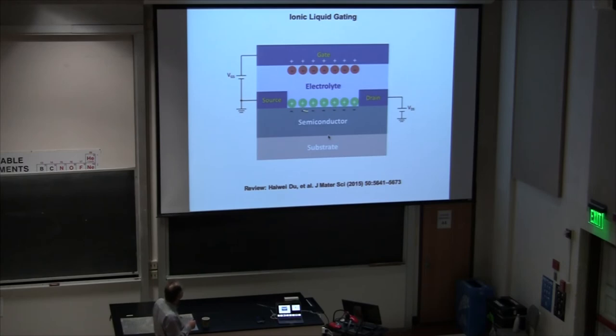This is a cartoon. I'm now convinced that this cartoon is never right. But this cartoon is still out there. I think only a handful of people now believe the cartoon is always wrong. Some people will admit that it's wrong in some cases, but I think it's always wrong. What I think is happening, it does work, in other words, you can metalize these things, but I think what you're doing is actually intercalating hydrogen into the materials. I think you're putting hydrogen into the materials, and that dopes them.